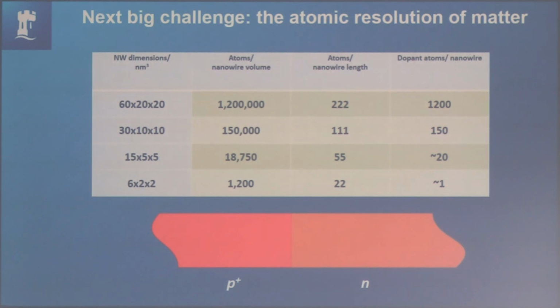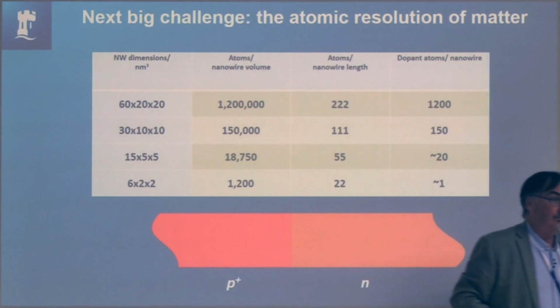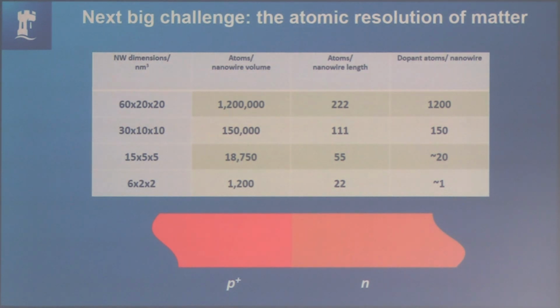That's the number of impurity atoms that I need to make it either p-type or n-type. But as we go smaller and smaller, if I have a nanowire that's 6 nanometers by 2 nanometers by 2 nanometers, and I want to maintain that doping, I have to have precisely 1 dopant atom in the nanowire. That's tough when you're trying to do 100 billion of these things on one chip, right? It's quite a challenge. We're not far off that point.